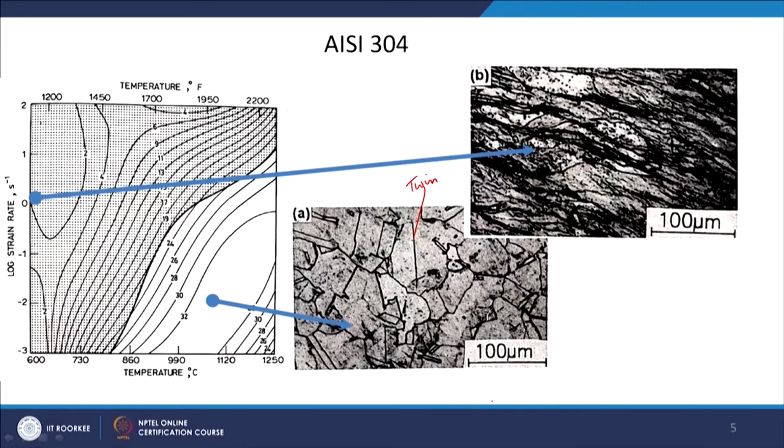And of course, the microstructure is again recrystallized. So, there is no issue with this microstructure. In this processing condition I should get this kind of microstructure, whereas in the unstable region, where it is at higher strain rate and lower temperatures, you can see a lot of flow localization has taken place, all these dark regions.